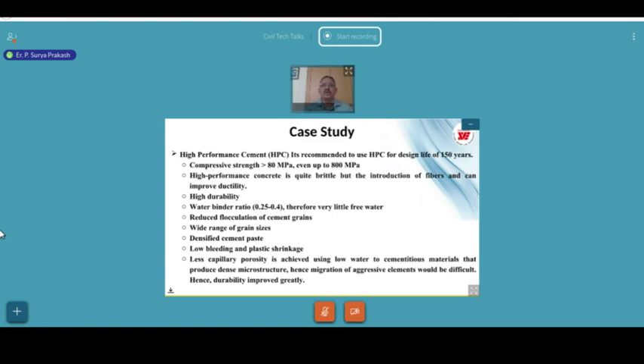Next is the high performance concrete. It's recommended to use high performance concrete for 150 years, because even for our infrastructure projects like metro or bridges, we use high performance concrete for 100 years itself. If it is 150 years, we have to have the high performance concrete, and preferably higher compressive strength, not for the sake of strength, but if you go for higher strength, the porosity will be reduced. Reduced porosity will help in reducing the attack of the chemicals on the initiation of deterioration by corrosion. And high performance concrete is quite brittle, but the introduction of fibers can improve ductility, and high durability of the concrete has to be ensured.